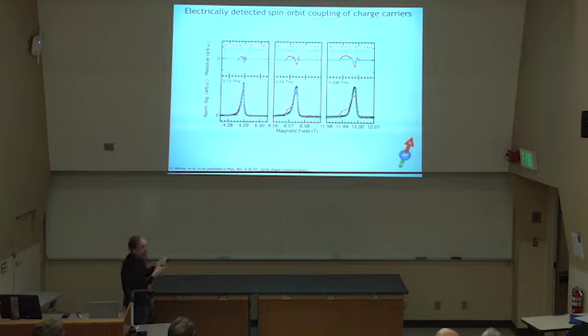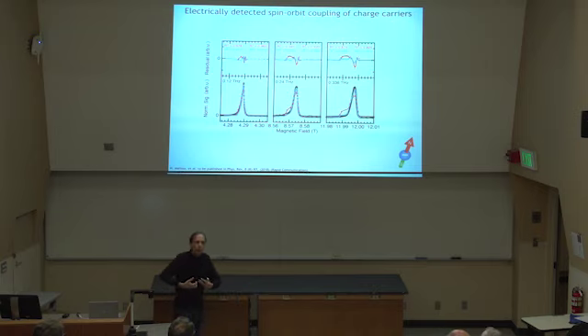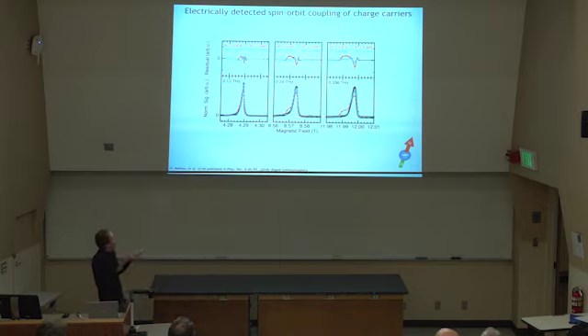And that essentially tells us that this data contains really unambiguous information about the nature of these wave functions. The wave functions are calculated, but here we have an experimental way to scrutinize those. And that's what we've done. So essentially, you can say you measure your wave function, which of course you don't, but you measure data that can be scrutinized by DFT, where your DFT predictions can ultimately be tested.